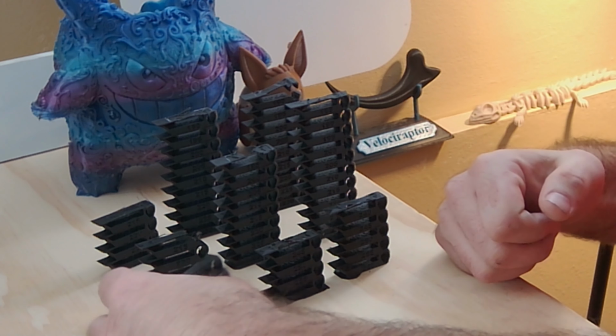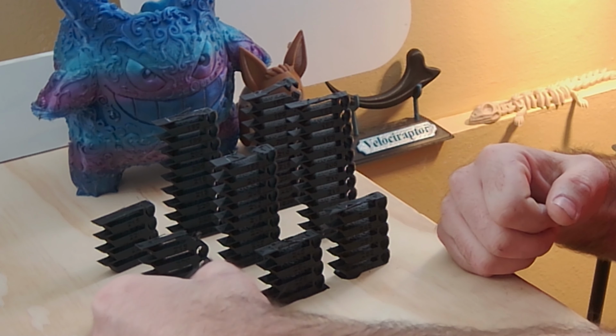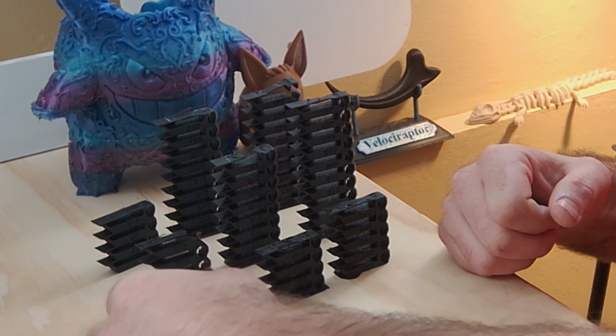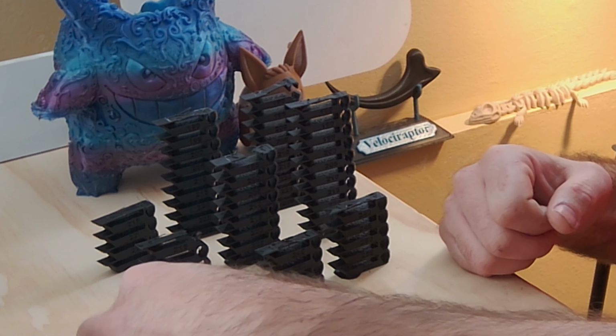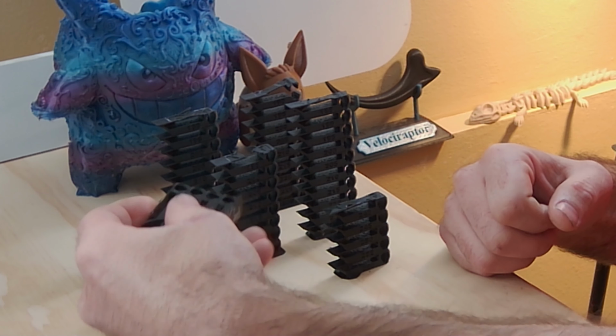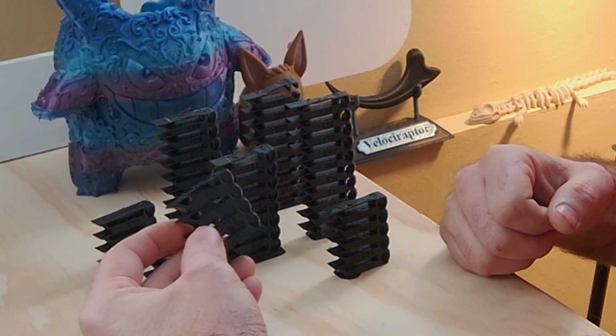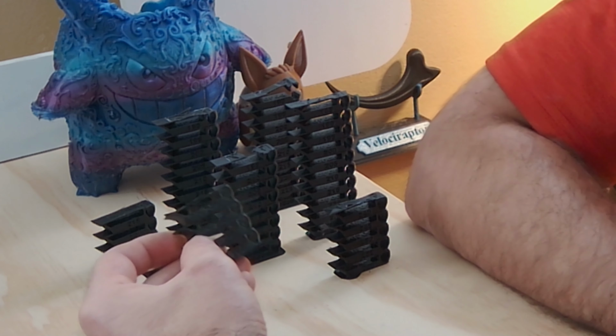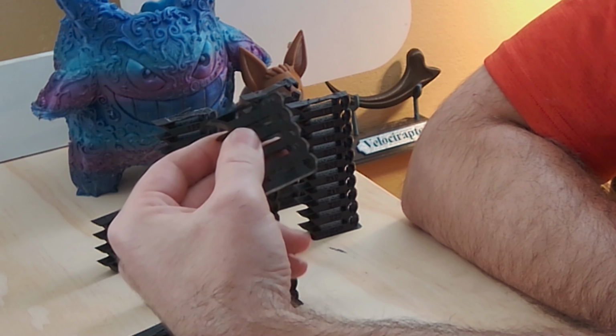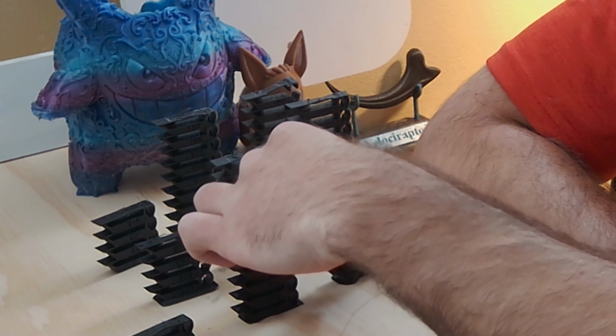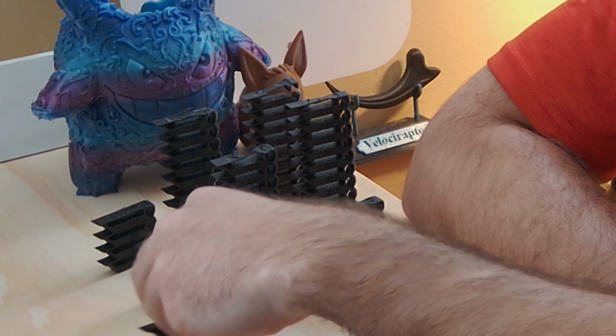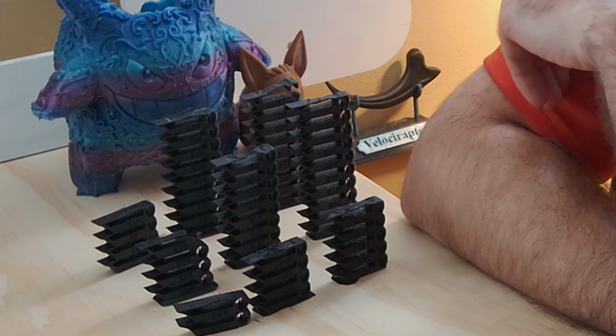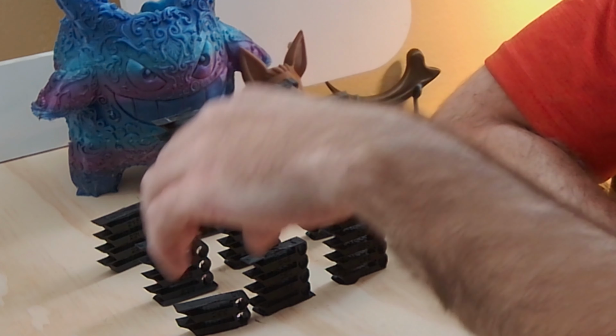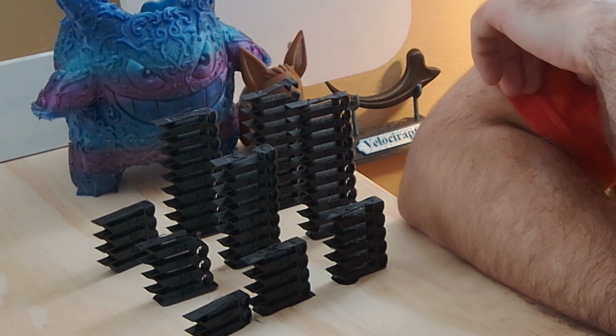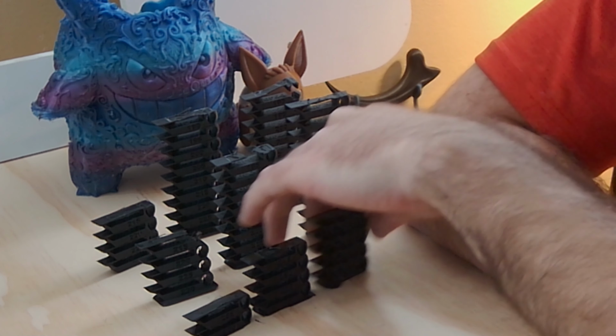So with PETG, hardened nozzle, very, very weak. I didn't have any strength in it really up until about 250. 255 held great. With the copper nickel nozzle, we really didn't have strength until 240, 245. And then we were able to get strong at 240 with the diamond nozzle. So results pretty impressive. They do show that the temperature does matter quite a bit, and depending on what nozzle you have will change the strength of your parts.